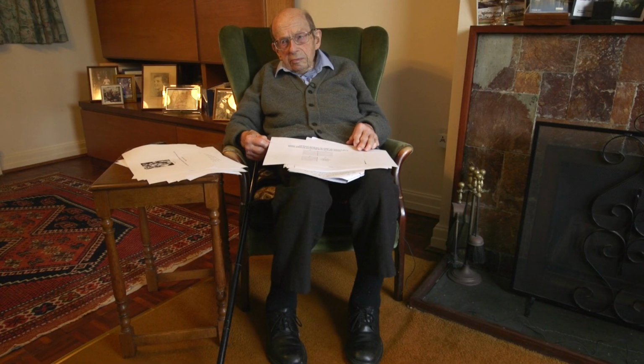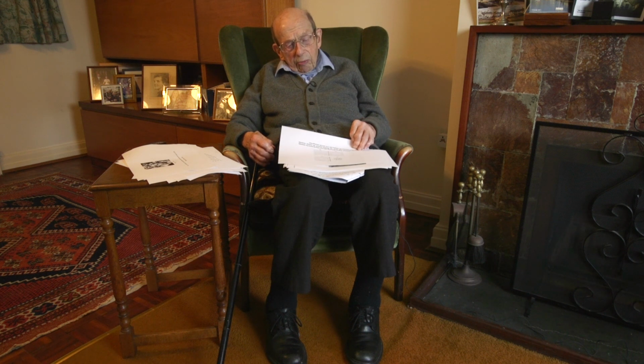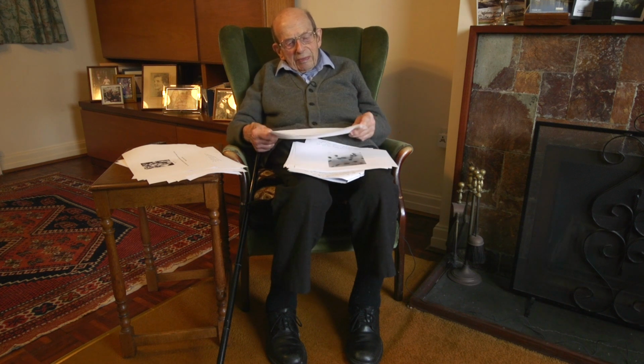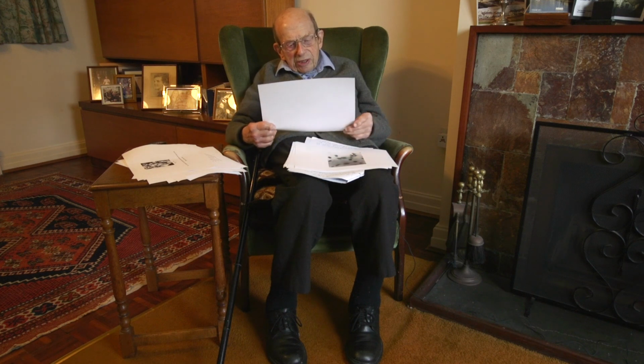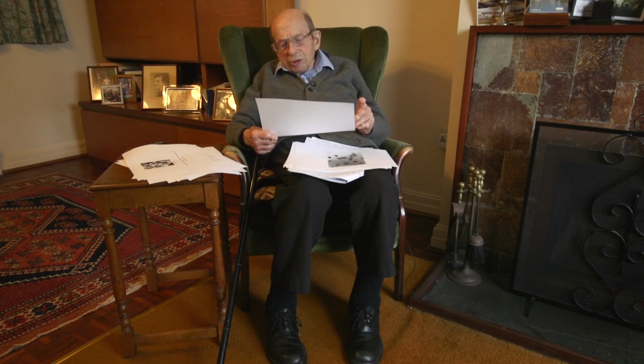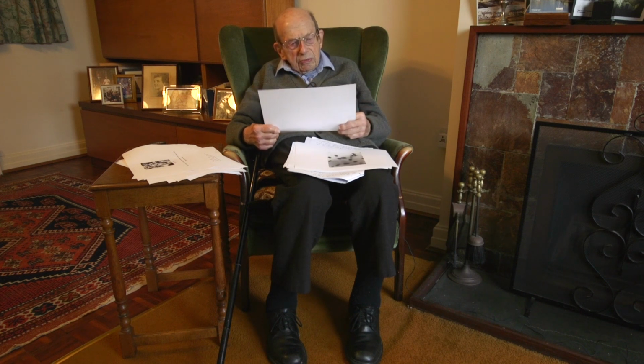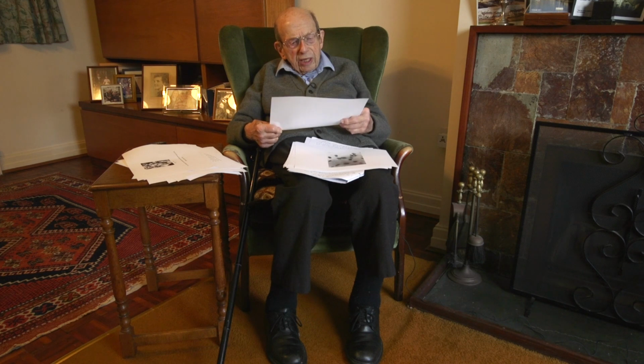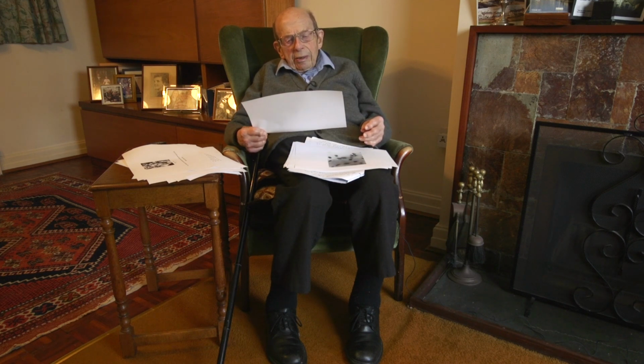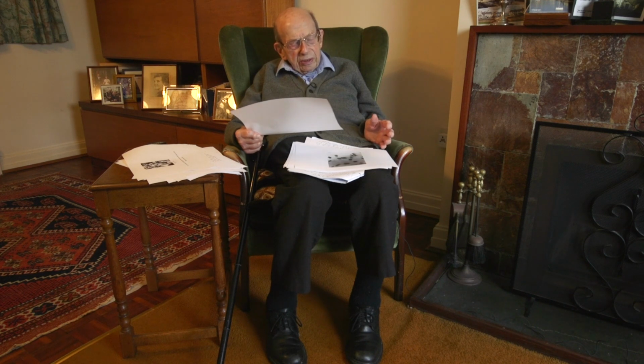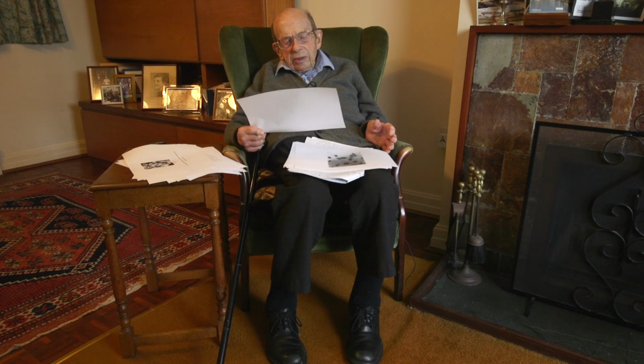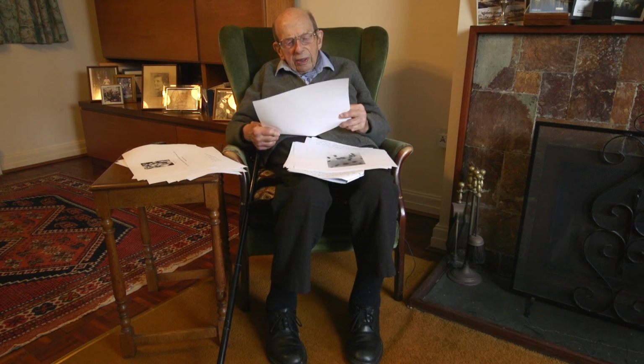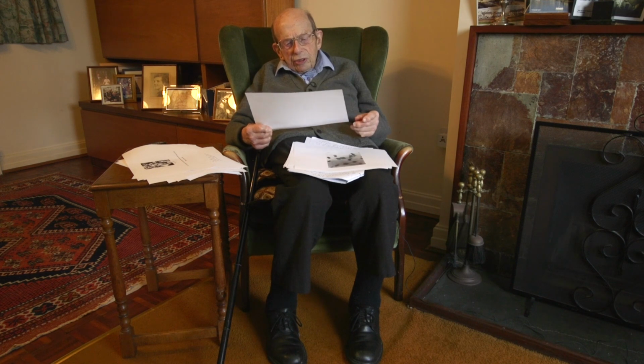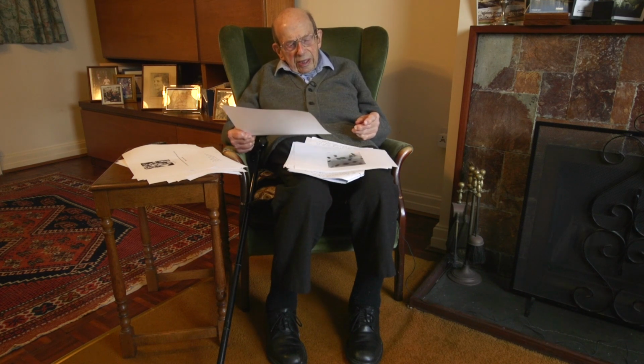Were there key applications? Were there technologies that were being developed which made use of this? Well, there was, and I'll come to that in a second. Before I do that, I want to show you an effect where you could see a direct effect between what happened to the material and the deformation and the defect structure, and that is quench hardening.